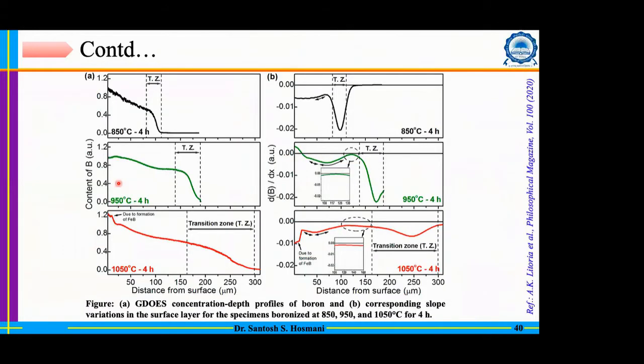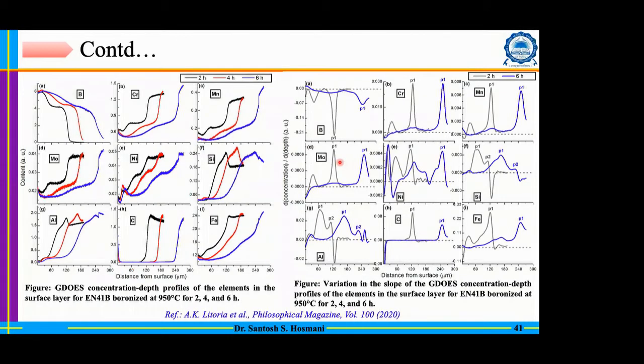And temperature-wise, you can see the effect of that: the transition zone becomes quite wide here. In the case of 1050 degrees Celsius, the transition zone is almost 50% of your entire boride layer thickness. And the slope is approaching zero. That means you have some stagnation there, and this stagnation is linked with the accumulation of aluminum and silicon in the matrix, which you want to avoid. And that is happening because of slow migration kinetics.